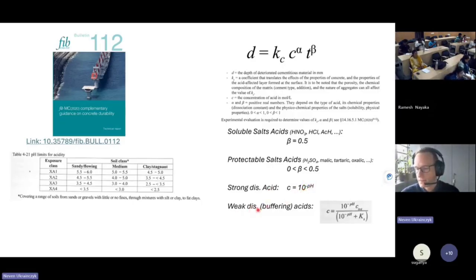But if you have a buffering acid like acetic acid, then this is the way you can calculate the pH from the concentration, or the concentration from the pH, because this is a weak acid. Weak means that it's weakly dissociated. It's not weak in the sense that it actually even has a buffer effect. Weak means that it has a weak dissociation constant. That means the pH is higher, but you have a high amount of buffer that can then provide more protons, more H+.